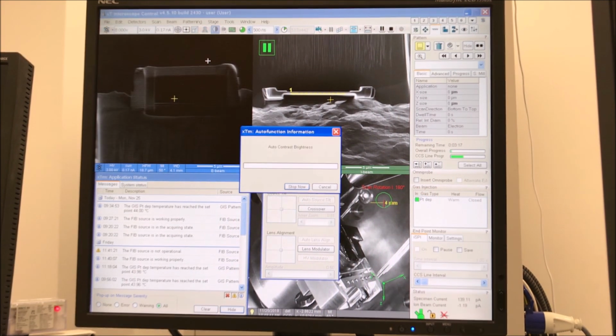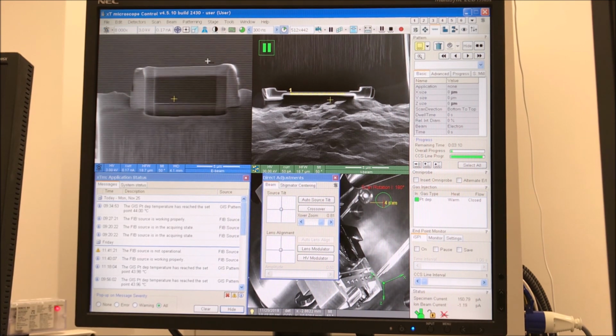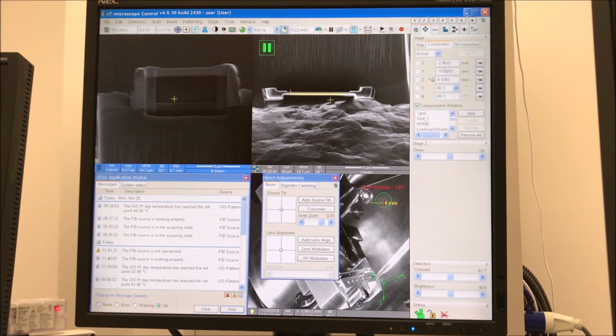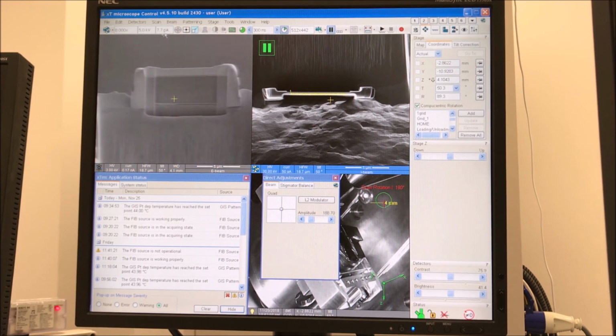And it's a little tougher to see because now we're milling the side of the lamella we can't see in the E-beam. But as the lamella gets thinner, you can start to see the millings that you're doing from the non-visible side in the E-beam, although we really can't see that yet here. But it will become more evident as the lamella gets thinner. And once this step is done, the ion beam voltage will be reduced to 5 kilovolts for the next 2 milling steps to reduce the damage layer to the specimen.